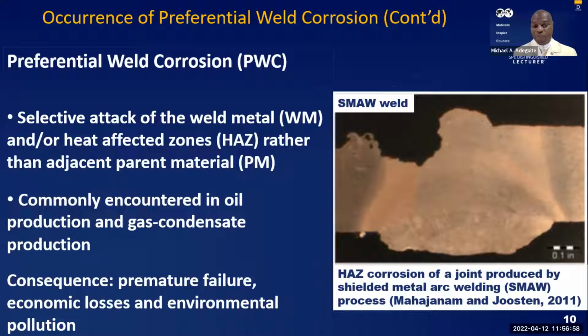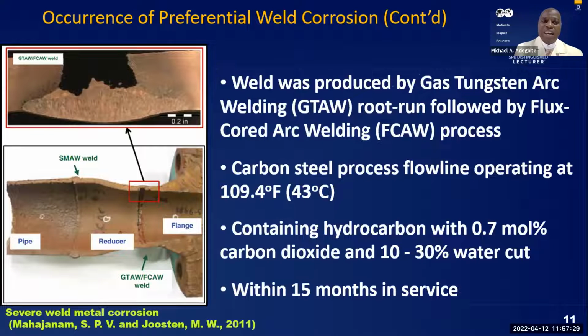So it's commonly encountered in oil facilities, and the consequence, of course, is premature failure, economic losses, downtime in terms of production, and of course, environmental pollution. And a typical example here, we can see the weld metal going into solution rather than the parent metal. So in this case, we have the weld metal selectively corroding compared with the heat affected zone and the parent metal. And this happened within 15 months in service. We can see that this led to a failure around the reducer and then a shutdown.